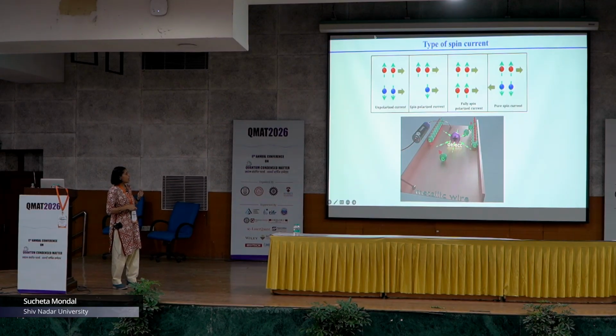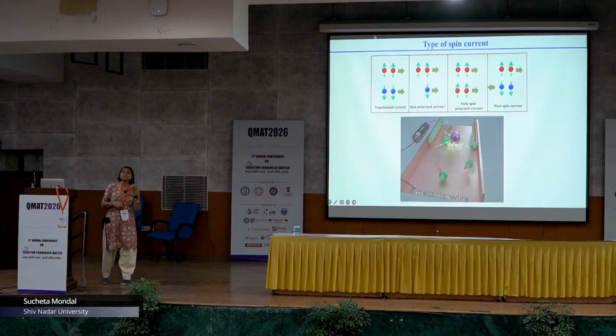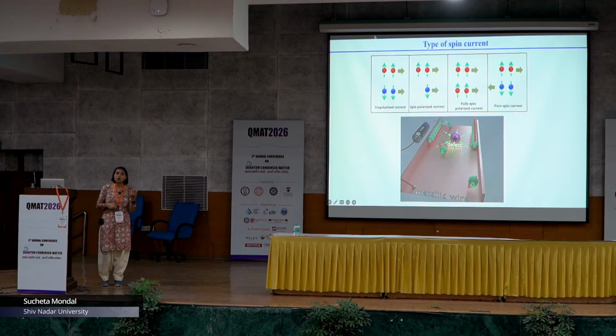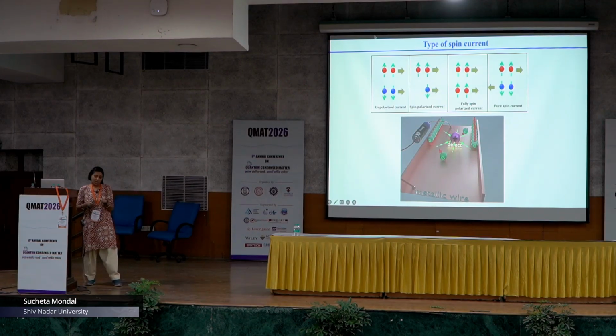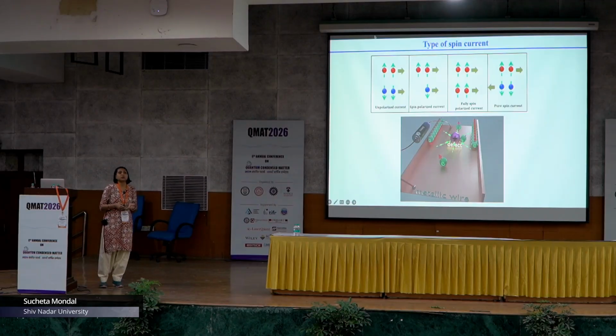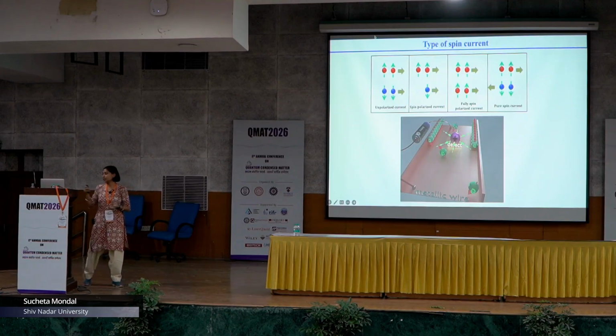In that case, what happens is that the up and down spins with opposite polarity get deflected in opposite directions. So, that will create a spin imbalance. So, without any charge imbalance, if there is a spin imbalance, that is called the pure spin current. And the spin Hall effect and also the spin pumping effect are examples of such spin current.